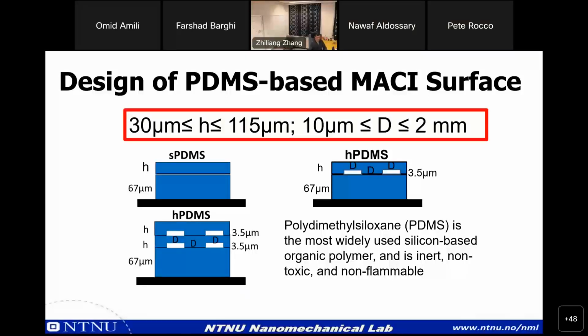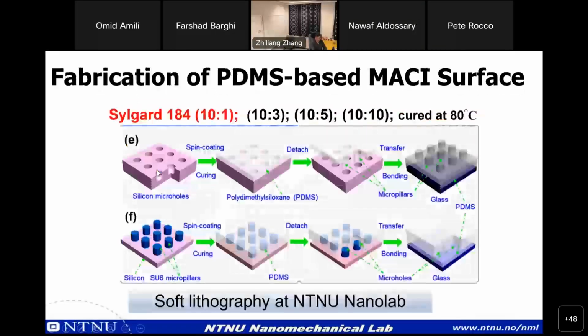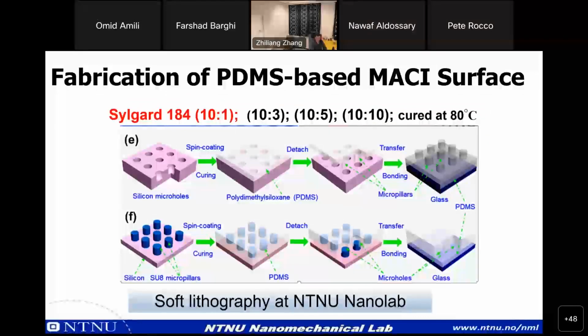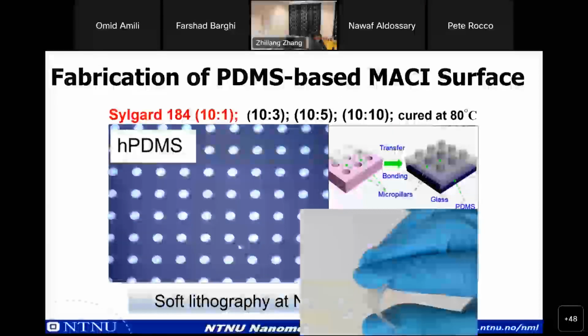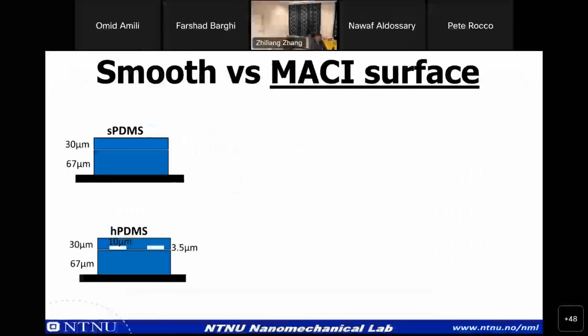We have chosen different structures. D is the width, the same as the spacing D here. So we have a single layer, we have a double layer. So we have a bottom layer of 67 micrometer, and we change the H as well. We use our lab to fabricate the coating. I'm not going into details here. These are the coatings we have fabricated.